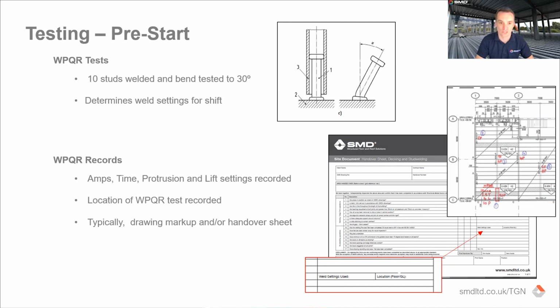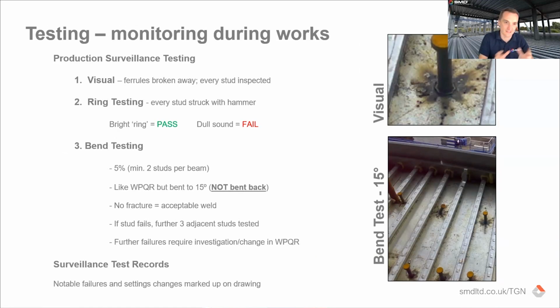If they fail, you obviously change your settings until you get settings where the consistency of the weld is good enough. And typically that will be good enough nearly first or second. Usually you don't need a lot of moving the settings around, purely because the WPS has pre-qualified those. And that information should always be recorded on the handover, or it may be on a marked up drawing. So you can see we have a section on our handover for weld settings used and the location, and you can also mark up the drawing as well. Different people do it different ways. So that's the testing for, okay, what settings do I use today?